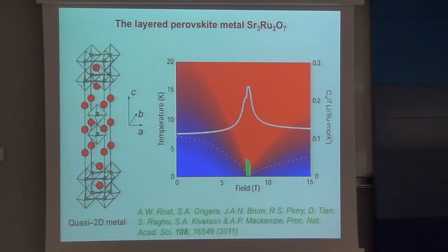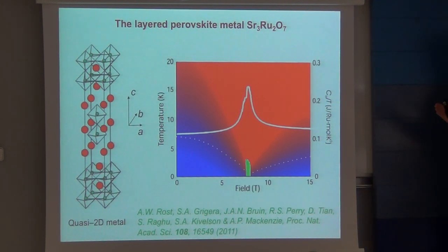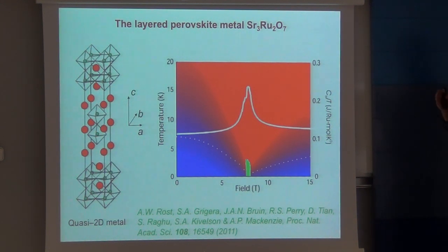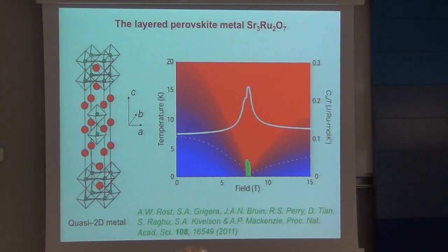So in the language of this bandwidth and crystal potential, the interesting thing is that quantum criticality is also a way of changing the bandwidth. So you're using the magnetic field to tune the quantum critical system, you're reducing the characteristic kinetic energy scale without, to first order, changing the lattice potential. So that's probably why you're able to frustrate all of the interaction, the kinetic energy and the lattice potential. It's by playing this quantum critical game.